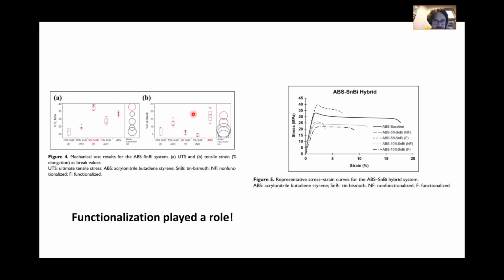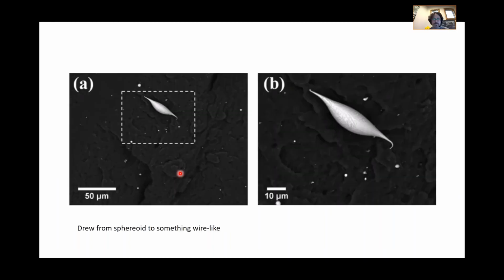I can see that a little better looking at this—the mean, yeah, I'll guess around 18 in terms of the mean. These stress strain curves were actually composite curves we made in MATLAB, plotting the average of all our tests, which was kind of cool. This one was the standout winner, and again functionalization played a role. What happened was we drew the material from something spheroid into something kind of wire-like.